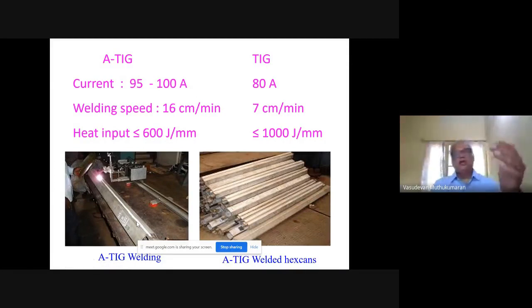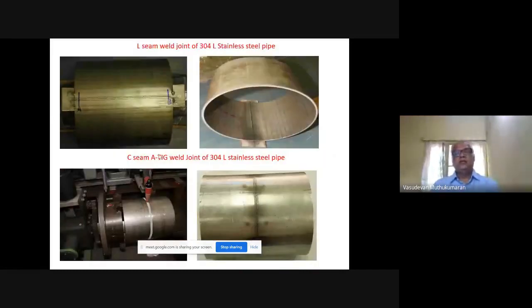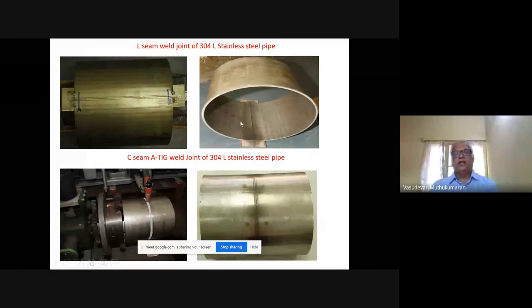We could reduce heat input, so we reduce resources and distortion. We have successfully fabricated these components and we have been using them for the last 10 years in our core testing facilities. Then we went on to do pipe welding. You can see here pipe welding. This is again 4 to 5 mm thickness pipe welding. You can see that we are seam welding the top side and root side, full penetration.